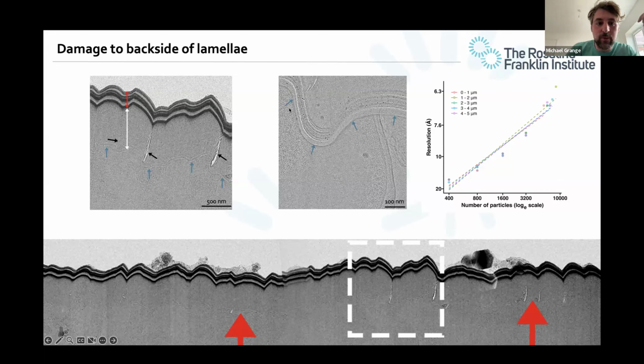And after this point where we see these structures generated presumably by the ion beam, you still have what looks like vitrified ice, but no biological densities. So the assumption here is that there's something happening when the ion beam interacts with the sample, which changes the structure of the molecules within the ice.